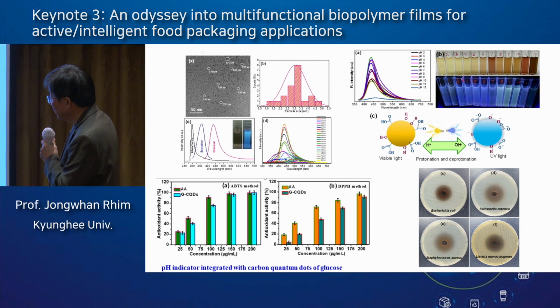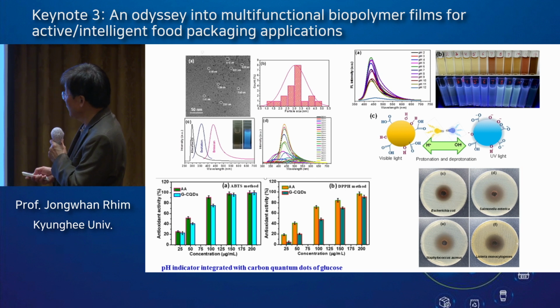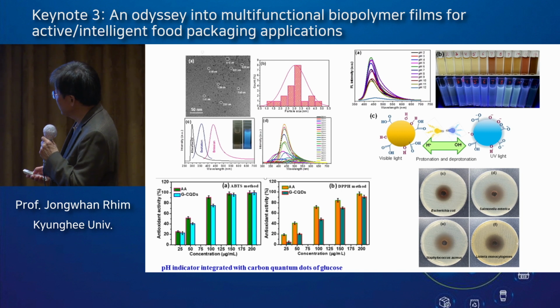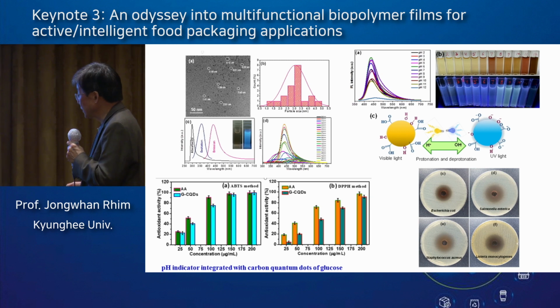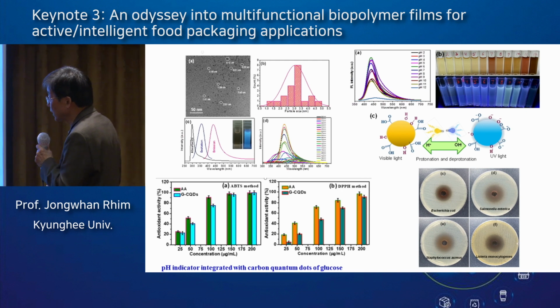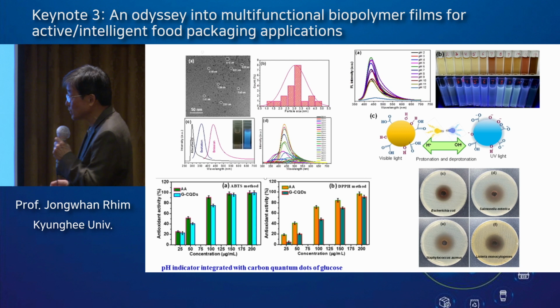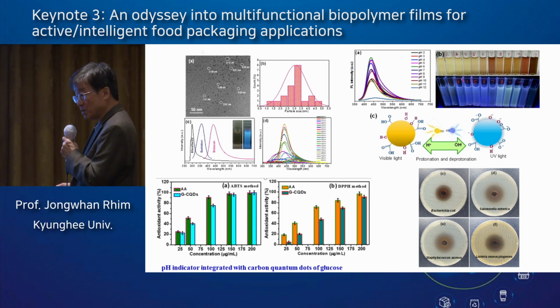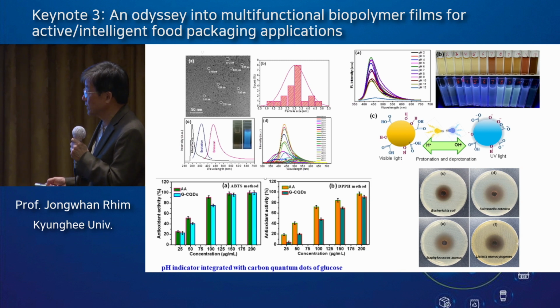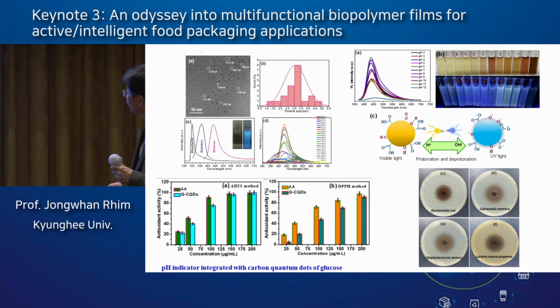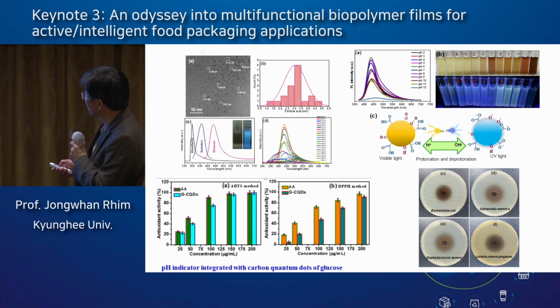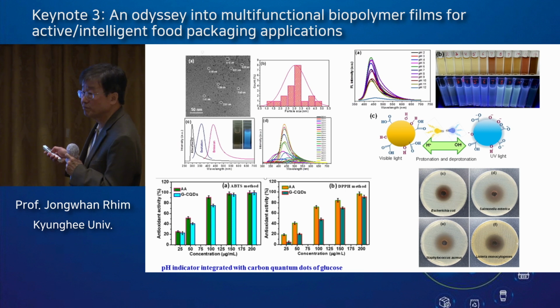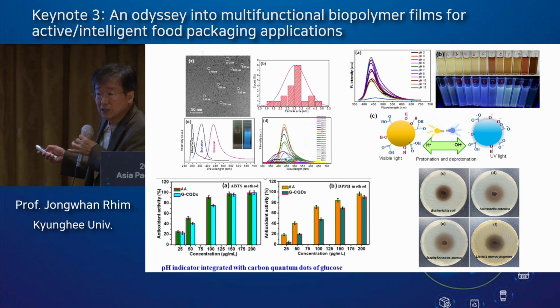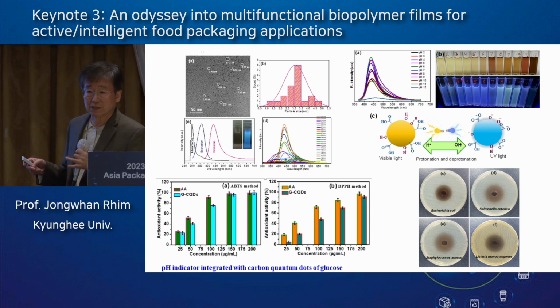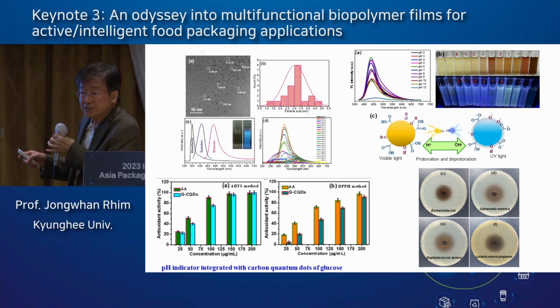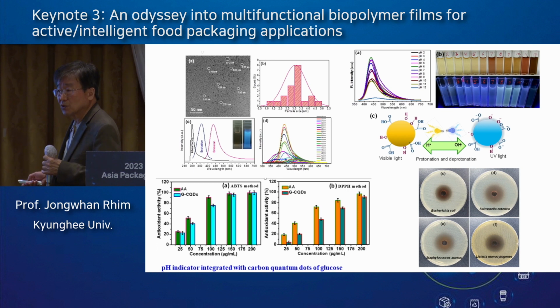We made carbon quantum dots using glucose and characterized the carbon quantum dots developed from glucose, and they show strong antioxidant activity by the ABTS method and the DPPH method. The antioxidant activity of carbon quantum dots is comparable to or higher than ascorbic acid. One interesting thing about carbon quantum dots is that they show color change depending on the pH. So they can be used for detecting the color variation of food material. They also show strong antibacterial activity like this.